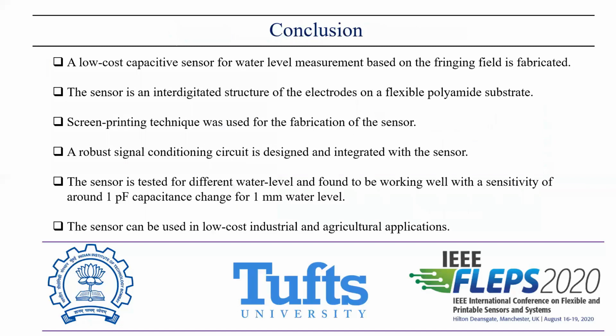So the conclusion is, we have fabricated a very low cost sensor for water level measurement based on fringing fields, and the sensor is interdigitally structured on to a polyimide substrate. Screen printing was used. A robust signal conditioning circuit was designed for the sensor, and the sensor provides measurements very accurately with reasonably good sensitivity. This sensor can be used in low-cost industrial and agriculture applications.